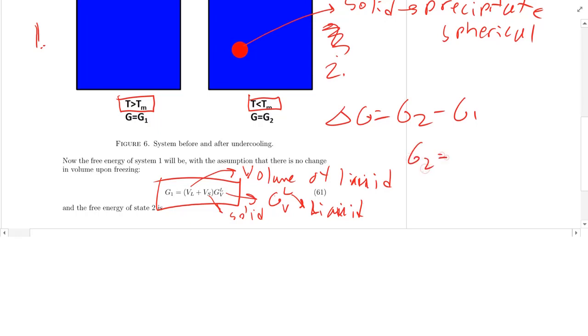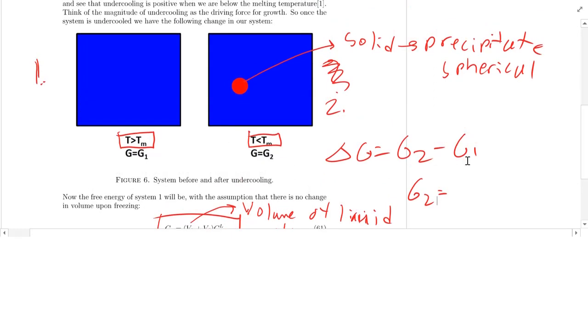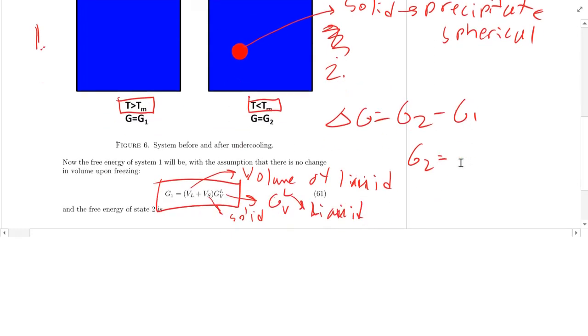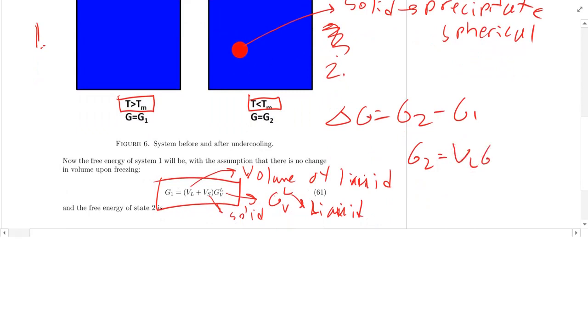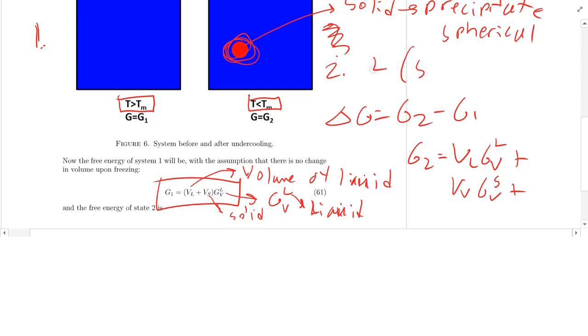G2, on the other hand, has additional terms. We have volume of liquid times GL, plus volume of solid times the solid-phase energy GS. The other thing is we've created an interface separating solid and liquid — this is bad. We account for this energy term as the area of the solid-liquid interface, ASL, times the surface energy gamma SL.